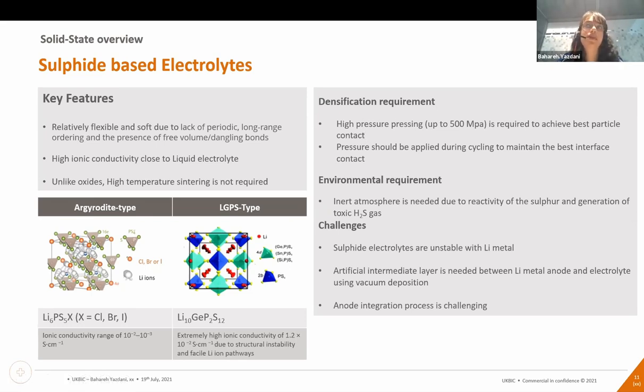So although they don't need high temperature sintering, they need high pressure for closing the contacts, and also most of the time they need to be pressurized during the cycling as well. So pressurizing can again increase the cost of the battery modules for sulfide-based. And the environmental requirement is more critical for sulfides because they generate H2S gas, which is toxic.